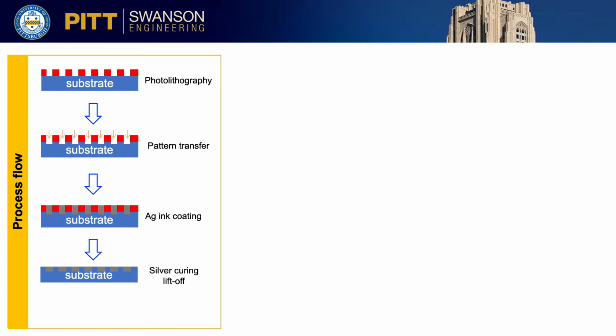First, for the lithography process, a nice pattern is formed by spin coating a layer of photoresist, a special polymer which is sensitive to visible light. Then development and exposure. A reactive etching procedure was done to expose part of the substrate. A particle-free silver ink was spin-coated onto the samples.